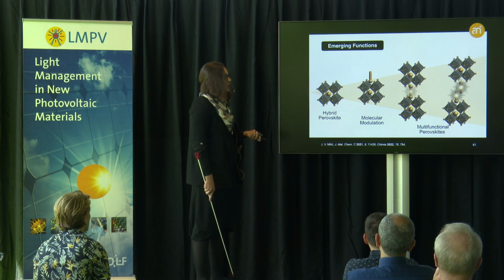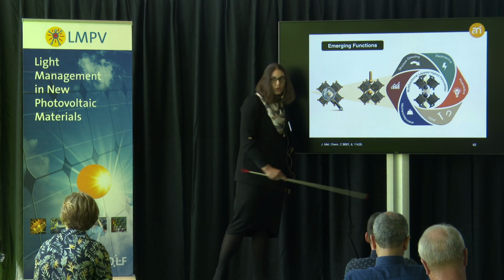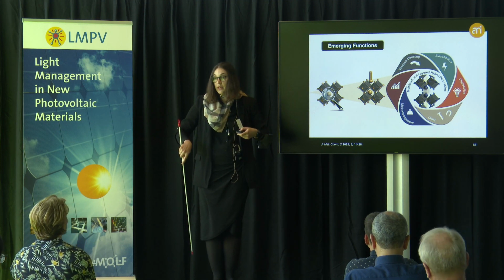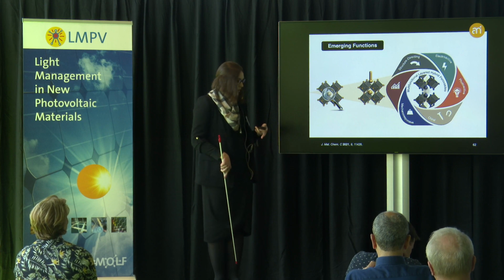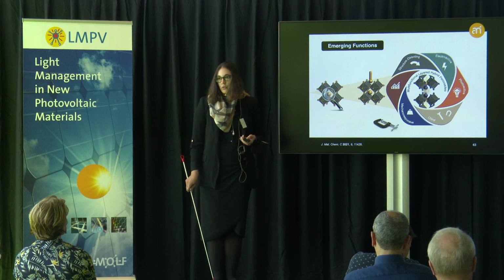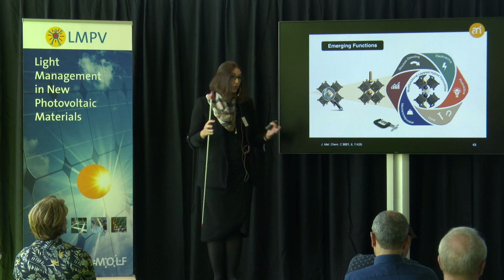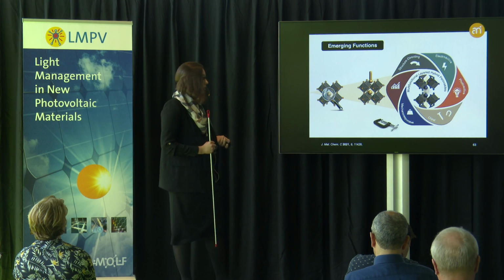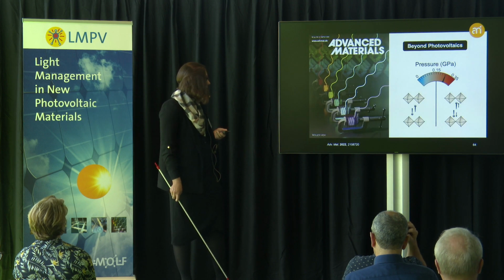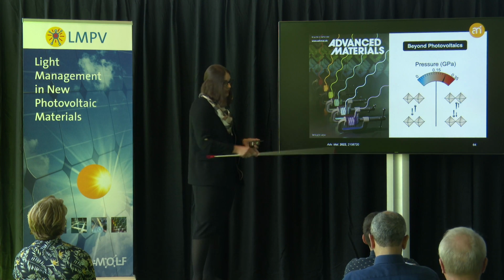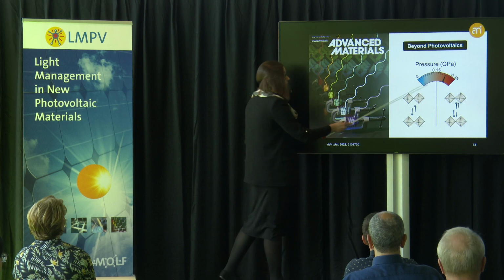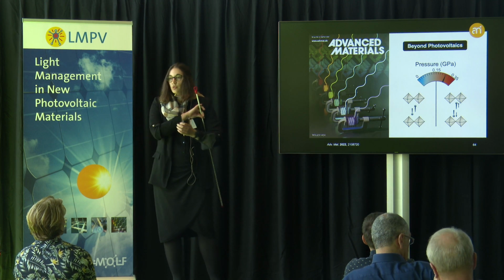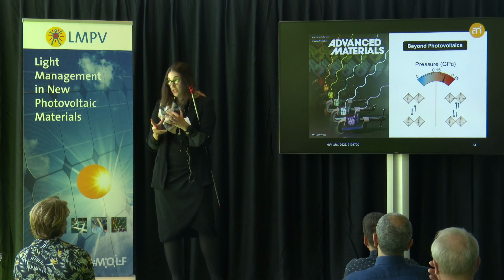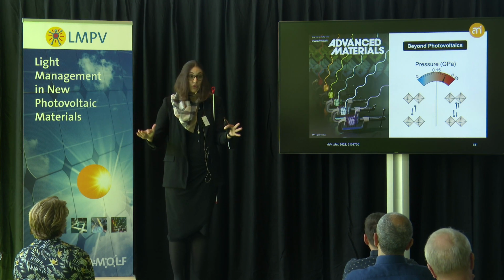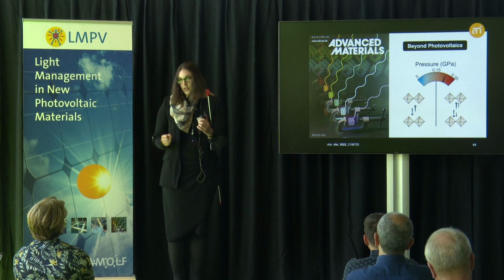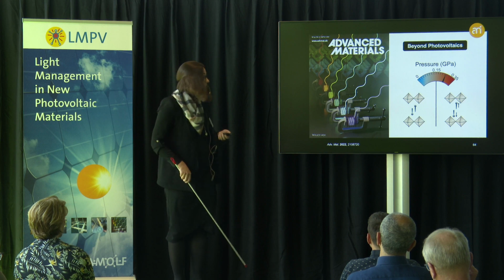So this involves a number of different functionalities, from electroactive, photoactive, chiral, or other moieties that can respond to different external stimuli, from charge, voltage bias, light, or mechanical stress or external pressure, as illustrated in some of our recent reports, suggesting that these dynamic structures could even reversibly change their properties, including the optoelectronic characteristics, as recently illustrated by this example coming from a beautiful collaboration, showing the possibility to really tailor their optoelectronic characteristics reversibly, even in these relatively low pressure ranges, which correspond to the level of strain associated with some of these structural rearrangements in these molecular systems, offering an entirely new platform for hybrid perovskites as framework materials to incorporate different stimuli responsive systems that can open the perspectives even well beyond photovoltaics.